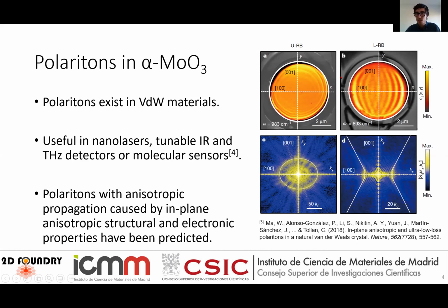In fact, this is a disk of molybdenum trioxide. And in these polaritons, you can see the interference with the edges of the flake, of the sample. And here you can see the dispersion of these two bands, and you see this anisotropic dispersion with the two bands. One has an elliptic type of dispersion, and the other has a hyperbolic type of dispersion.